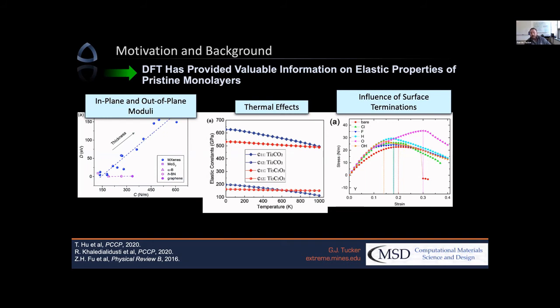Shown here, we can see that there is an influence of these surface terminations on the mechanical properties of these MXenes. But what we really need to think about here when you search the literature, and what we need to understand, is that real MXenes are not pristine, that we have these surface terminations as we've seen today, and it could be a complex distribution of terminations. It could be not one type, it could be multiple types, and they're not fully elastic either. We see MXenes that break, we see the failure of those, and so we actually have to think about that as well.